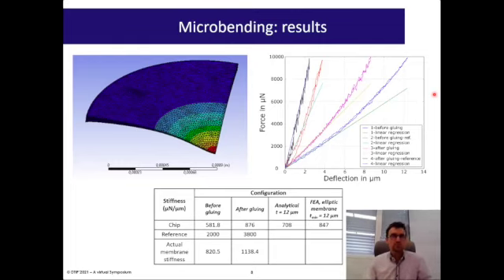From these curves, we extracted the stiffness with a linear fit at the beginning of the curve. And it has been seen that the model fits pretty well the experimental data. So here you have the two results from the two configurations, and here you have the models, the results that we obtained from the simulations.